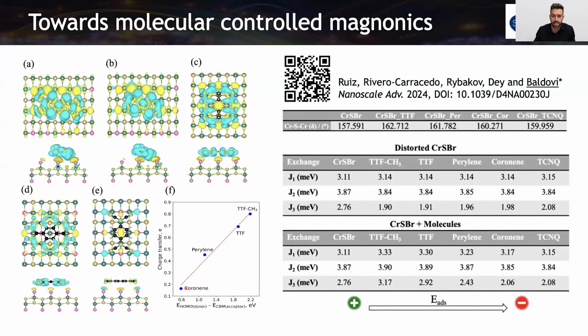And we observe this linear relation that relates, depending on the energy of the HOMO and the acceptor, we can predict the charge transfer that each molecule is going to donate. This is a perfect agreement, the calculation with the full system and this prediction with this subtraction.